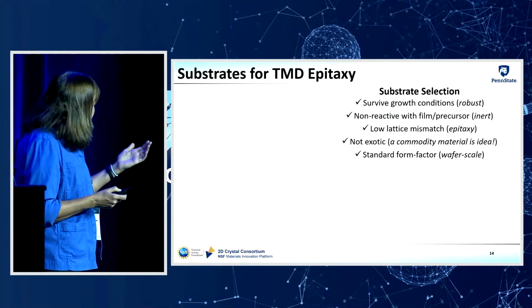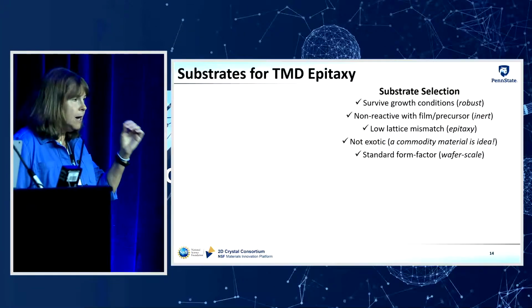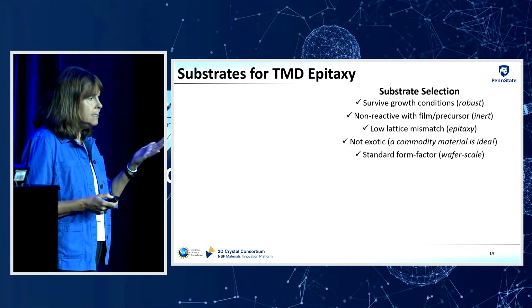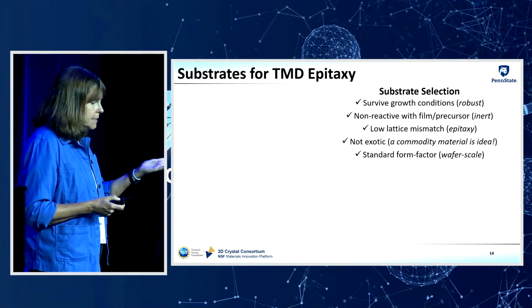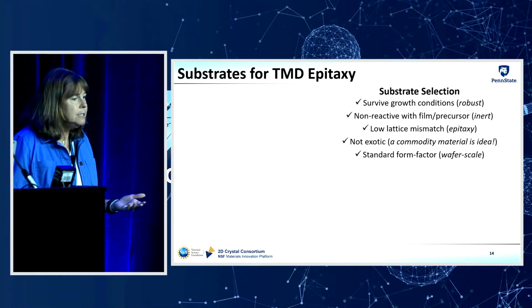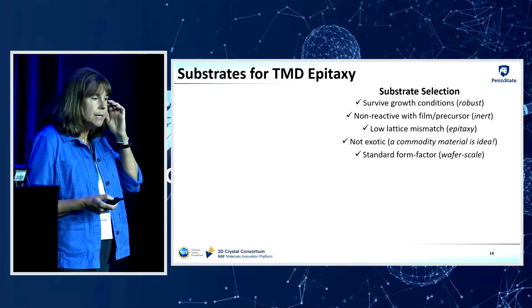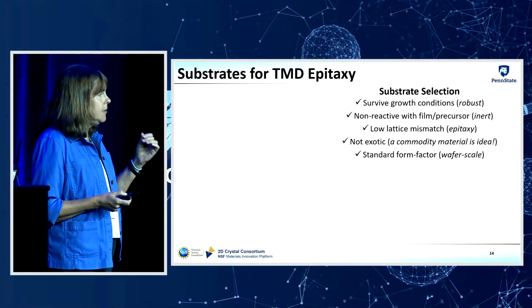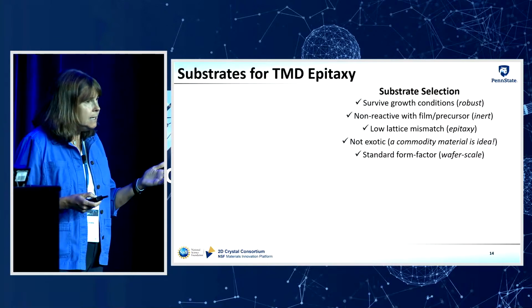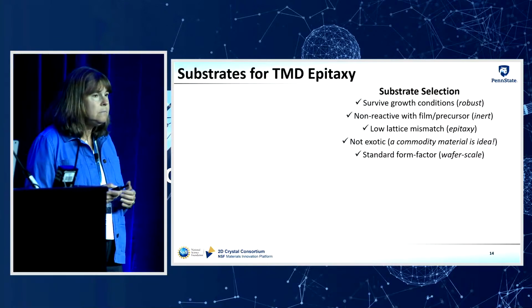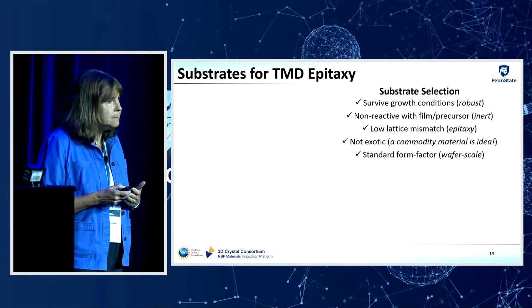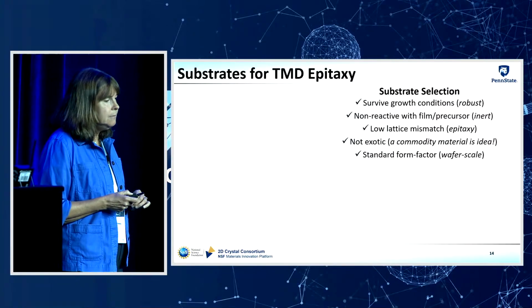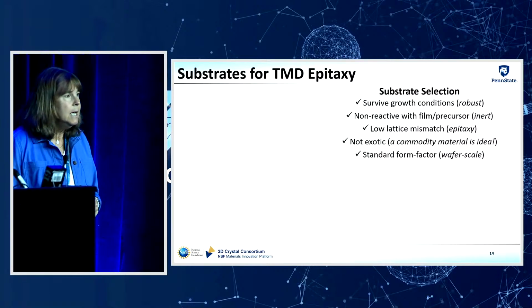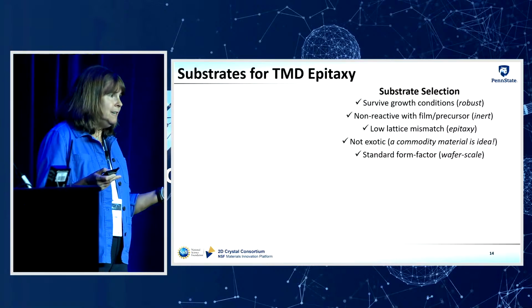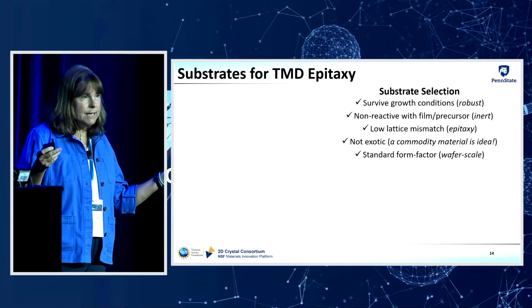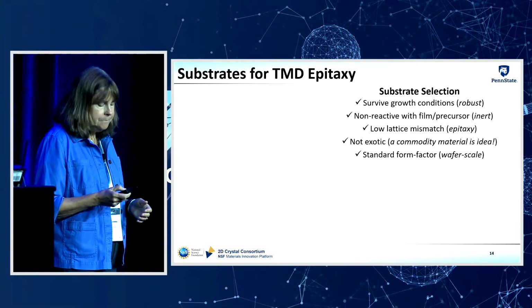So substrates are an important thing for epitaxy, right? You're using the substrate to template the orientation of your film. So there are some things that you have to consider when selecting a substrate. So the substrate needs to have a high thermal and chemical stability in the growth environment. It also has to have a low lattice mismatch to the film that you're depositing, right, in order for it to serve as a template. And then finally, it has to be commercially available, ideally in wafer scale sizes at a reasonable cost.